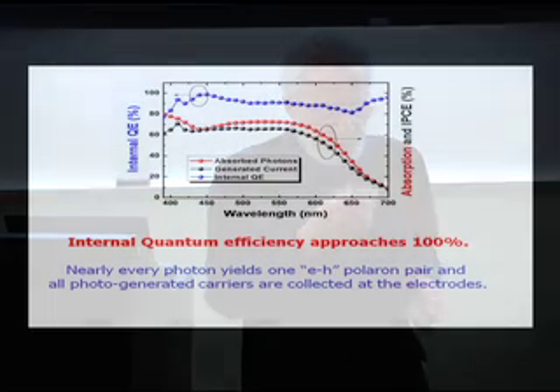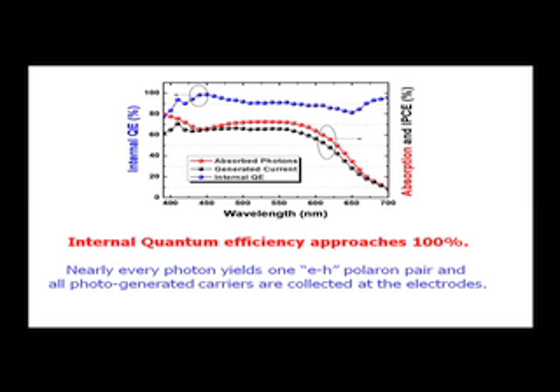And it allowed me then to say, well, okay, if that's true, we should be able to estimate what efficiency we really could get by an experiment. Okay? And the experiment is shown here. This is basically the spectrum. This energy gap is much too large to be optimum. This red light is coming through. So let's go here to the green light, right in the middle of the absorption spectrum, and let's make a solar cell that will test it with monochromatic green light. You get 17%. Just as the theory suggests we should.